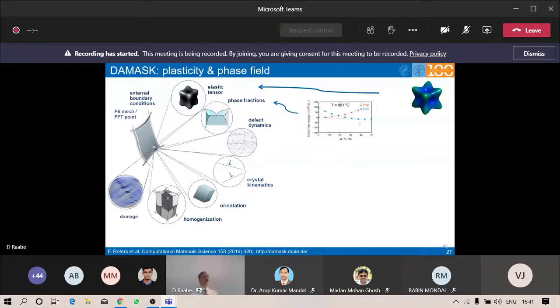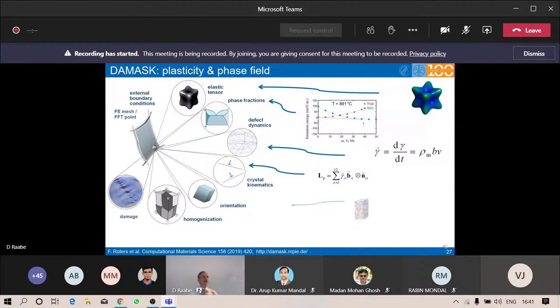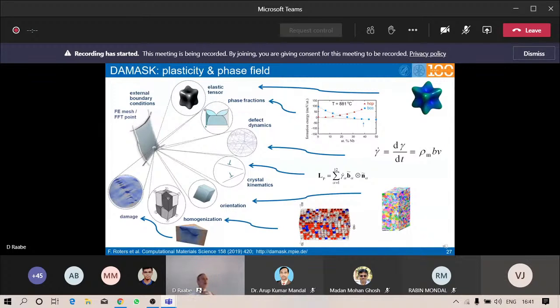And in DAMASK, we represent all these anisotropy features now at the integration point, be it the elastic, the phase composition, the shear rates, the flow equation I already told you, the Schmid factors in a crystal kinematic framework, the crystal orientations, and of course also possibilities to do local homogenization at a spot. When you describe a bigger engineering part, your point cannot describe a single crystal, but it must already describe an agglomerate, a mean field set of crystal orientations or phases that you homogenize and feed that information back to your integration point. And since recently, we also work on details of damage evolution, mainly with Pratheek Shanthraj, who is now at Manchester University, and with Bob Svendsen, who is at RWTH in Aachen.